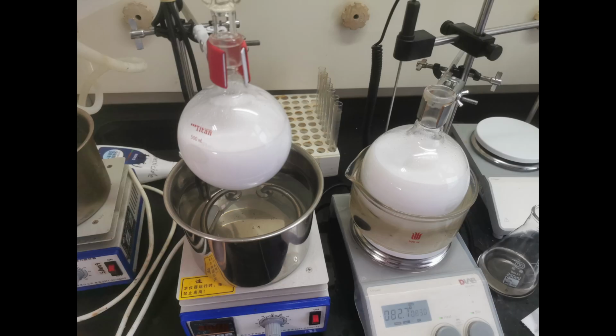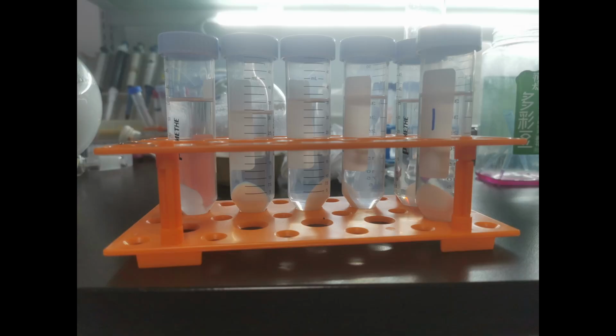After the hydrolysis is completed at 80 degrees C for 2 hours, the product is separated by centrifugation at 11,000 rounds per minute for 5 minutes, washed with ethanol once, and centrifuged again. The insane centrifuge speed and duration is necessary because the nanoparticles are extremely small and easily suspend in the solution, and consequently made this step by far the most annoying because I have to centrifuge a liter of liquid twice while using 50 milliliter tubes at a time.